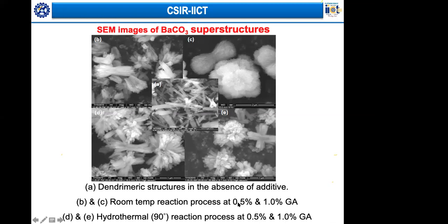Here we have taken 0.5%, and here 1.0%. Depending on the concentration, you see a difference. It's generally only rods here, but here you see these rods assembled in the form of dumbbells or something like that. These are hydrothermal conditions. These dumbbells at normal conditions have a different shape, a well-organized shape here, which is better than this. Okay.